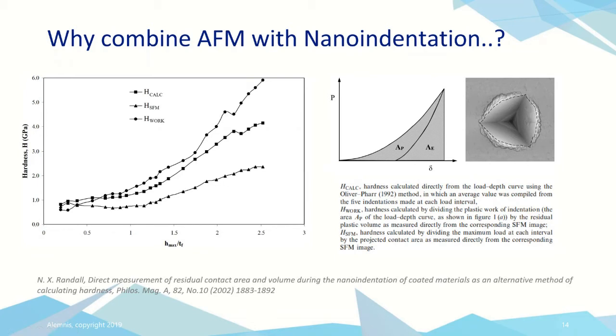And that makes sense, because when we start to take into account the pileup, then we've got a larger area for the same load, and therefore we're underestimating the hardness, if we like, or getting a lower value, which is what we see here for HSFM, which is the bottom curve. So very interesting to understand what's going on at the interface.